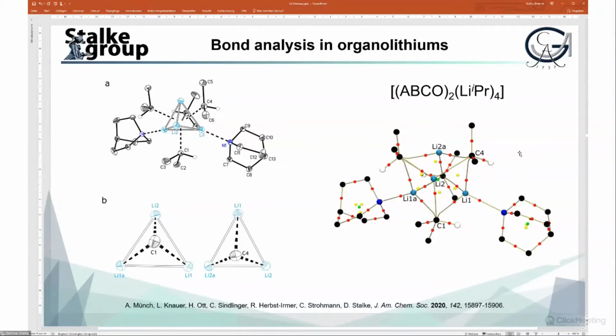So if this was a hint for bonding, because you need to have a scalar coupling contribution to bonding for NMR coupling, then yes, the bond path is real, and yes, the absent bond path between the lithiums is real as well. So we could find all the bond critical points, all the ring critical points in yellow, and all the cage critical points in green.